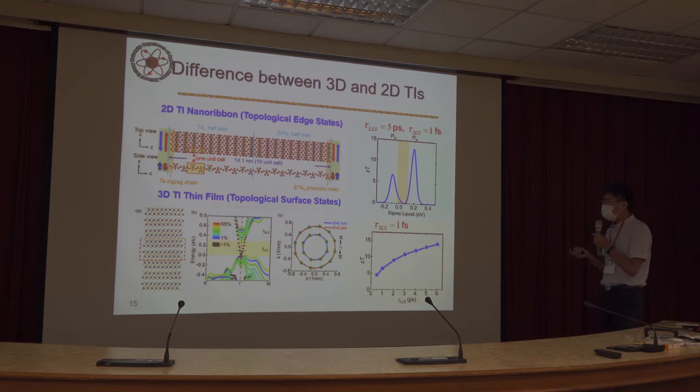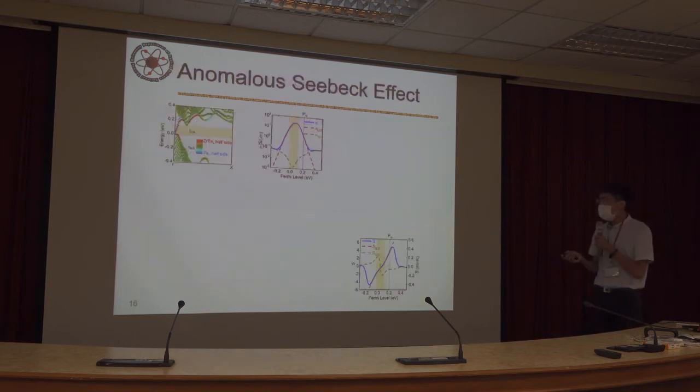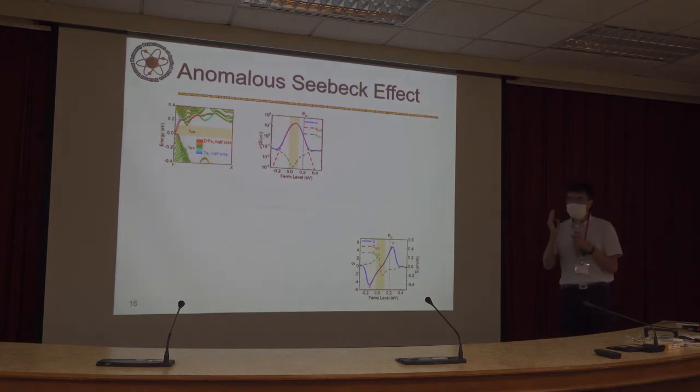And in fact, we also calculated the ZT as a function of the long lifetime relaxation time. We find even if the long lifetime relaxation time is as low as that comparable with bismuth selenide, the resulting ZT remains quite large, about 5 at room temperature. So now let's explore the underlying reason why it can have such a high ZT.